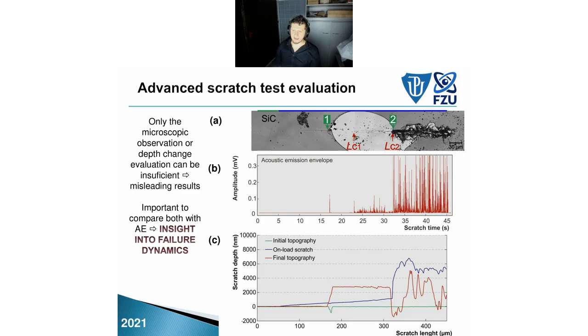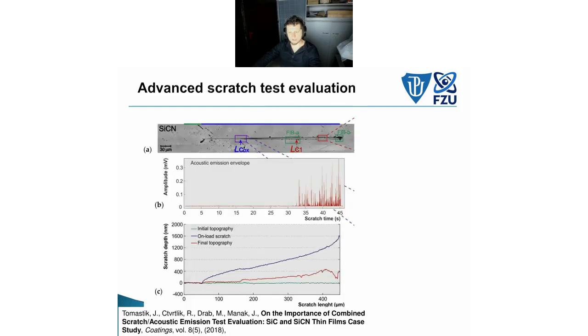So it can show us what we cannot see from microscopic images after the scratch, because if the coating did not crack backwards, we would probably not see it from the microscopic image. But we can hear it using acoustic emission, and the stronger signal here is the breakage of both coating and substrate. So only microscopic observation can give insufficient results. We need more insight into the system, into what's happening there, using the depth change record and maybe acoustic emission, which we are using very effectively.